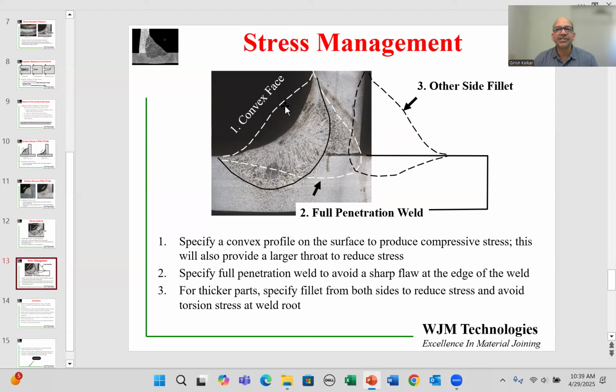But you as a design engineer can override that and be specific on your drawing that we must have a convex profile. And the convex profile eventually will look something like that when properly made with a dashed white line. The second thing you can do is to avoid this weld root. So this high stress point can be avoided if one of the components is fairly thin. Then you can specify a full penetration weld.